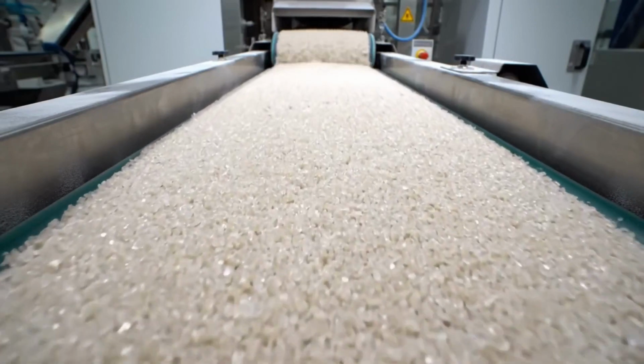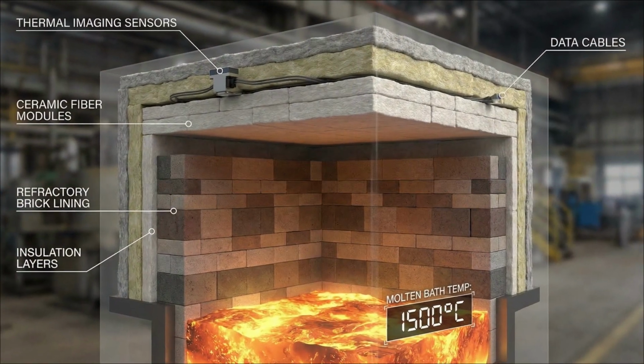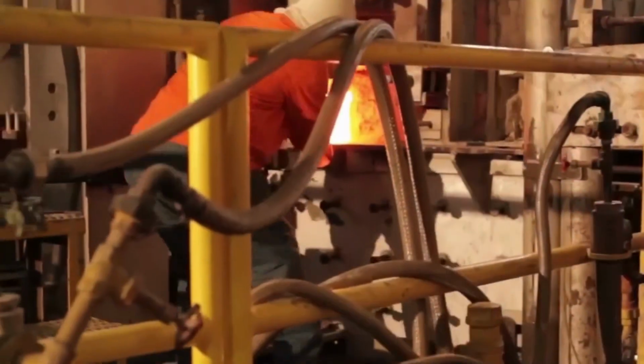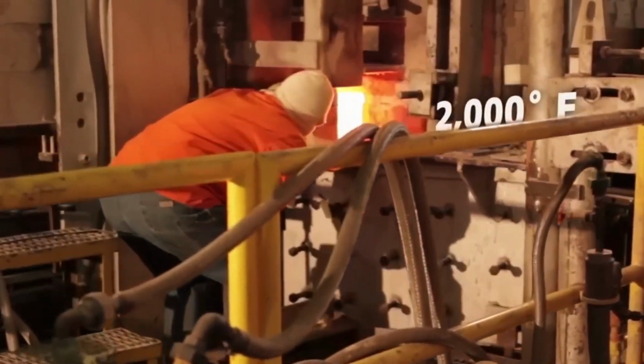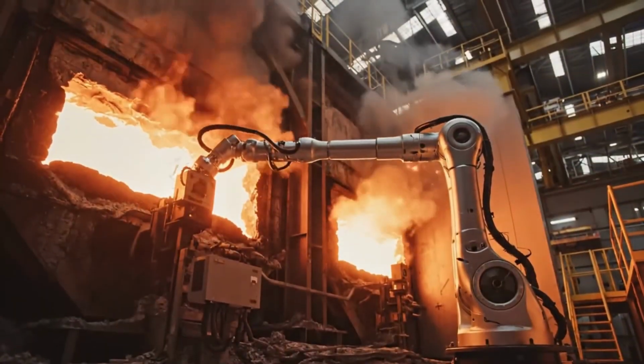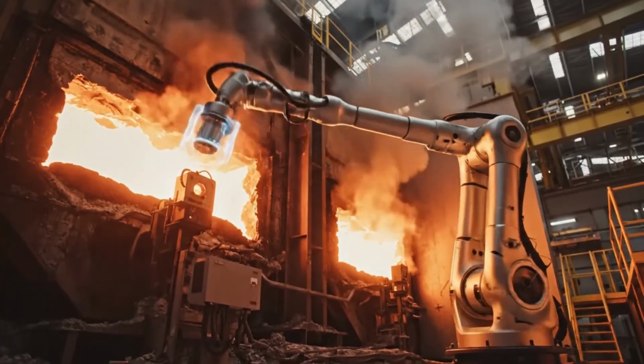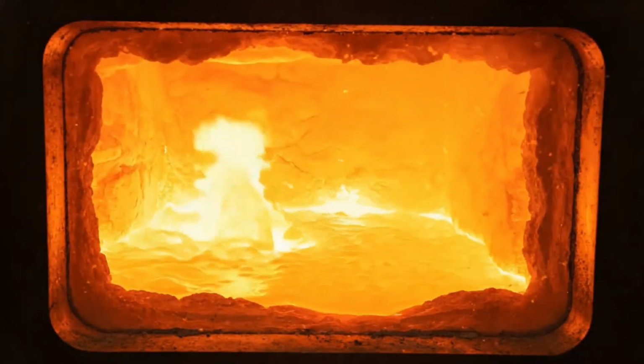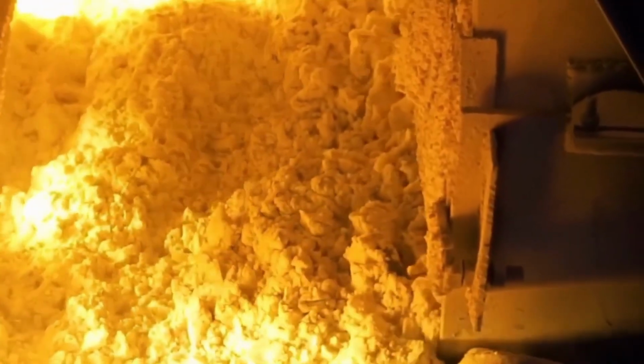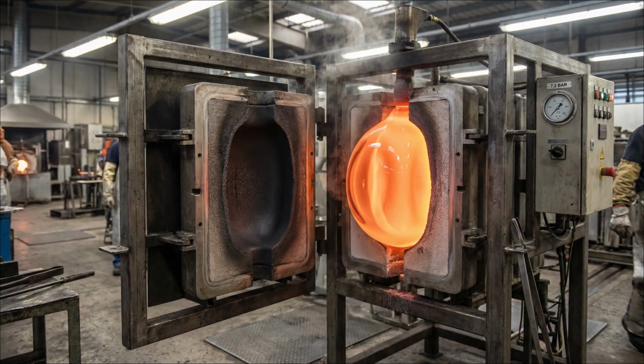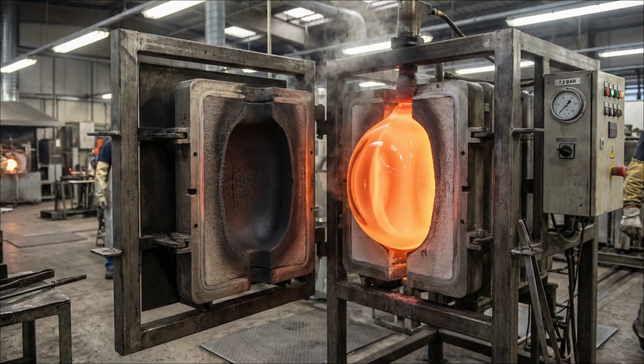If this furnace drifts just 10 degrees Celsius, every bottle shatters weeks later, even after passing inspection. Glass melts at 1,500 degrees Celsius, approximately 2,732 degrees Fahrenheit, but the real danger starts at 1,492 degrees. Drift 8 degrees too low, crystalline stones form. Drift too high, the furnace collapses. Here's the thermal battlefield that keeps molten glass alive.